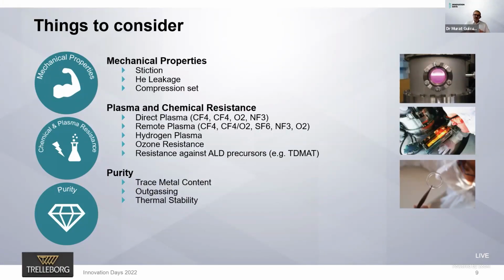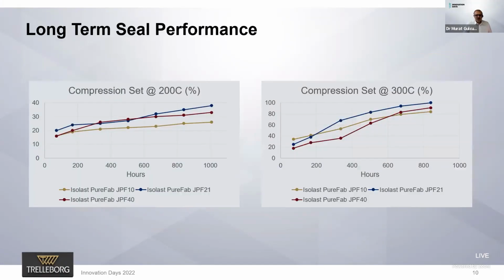In the semiconductor industry, on top of mechanical properties, plasma resistance and chemical resistance, there's another requirement, which is purity. Because, as I said, the device size is going down below 5 nanometers, which means it is extremely delicate. Therefore, trace metal content, the amount of metallic impurities, and outgassing are extremely important, as well as not releasing any molecules at higher temperatures, another way of outgassing. We have done all of this testing, even more than what you can see on the screen, and I'm going to share some of it today for you to have an idea about how our materials, especially PureFab materials, compare.